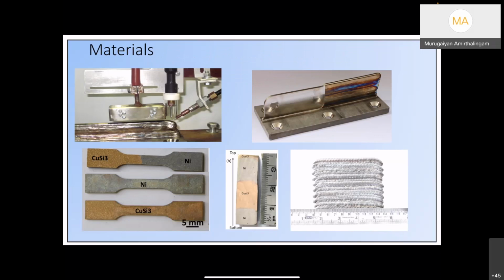So what material can we use in wire arc additive manufacturing? The thumb rule is that any material that is weldable, we can use to fabricate the component. Suppose you want to use a material whose weldability is reasonably good, and we can use that material in either gas metal arc welding or gas tungsten arc welding with filler additions, we can make a component out of it. So this is a deposition of titanium. After deposition, if you machine the surface to improve the surface finish, you get the actual component.